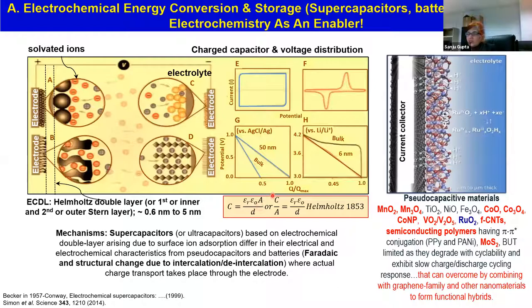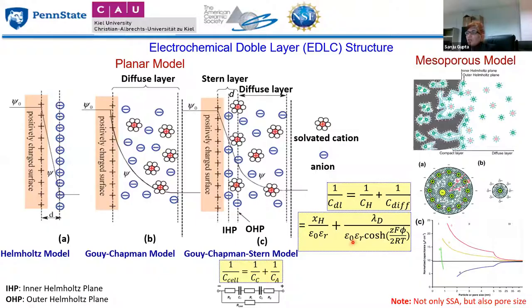I want to mention one more thing. As you can see here, this capacitance is directly proportional to the area. So it is not just the specific surface area, but also the pore size distribution. And that's why people started to make these materials very porous, because it was believed that the pore size has to be larger than the solvated ions. But later on, with theoretical calculations and MD simulations, it turned out that this is not true, because even the anion by itself, which is smaller in size than the solvated ion, is still able to store charge. So many new understandings of this double layer structure have come along in the last couple of years.